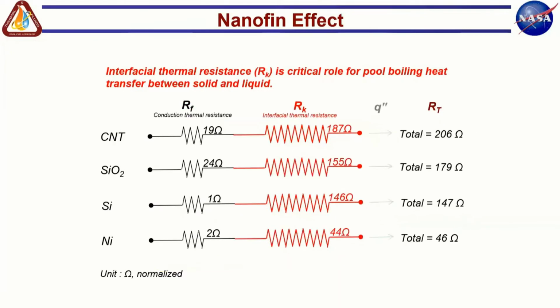So based on this insight, we came up with a hypothesis. We said that glass, silicon dioxide, is actually going to perform better if you make a nanofin out of glass compared to carbon nanotube. And then nickel, which is a metal, according to our prediction, was supposed to give us the lowest total resistance. And so therefore we predicted that a nickel nanofin will give you the best boiling performance compared to carbon nanotube. And silica, which is very heretic, if you tell this to the materials community, they will probably get mad at you. But silica nanofin performs better than a carbon nanotube nanofin, just because the Kapitza resistance is much lower for silica.